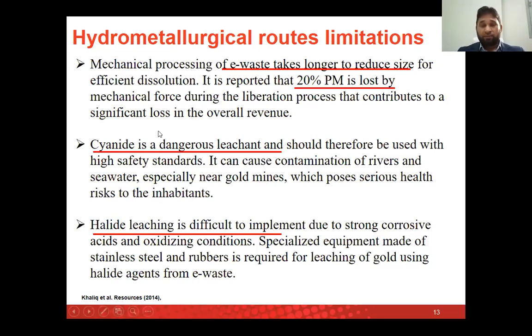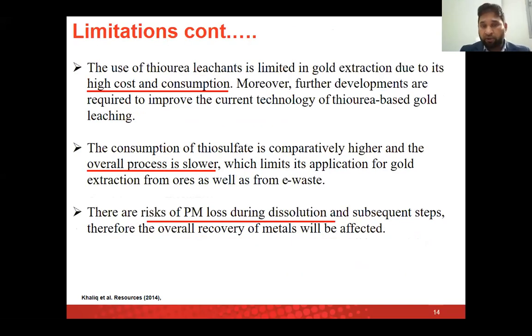Then the solvents or the acids that are used during the hydrometallurgical routes are not environmentally friendly. They are not recommended. Even cyanide is a very dangerous leachant. That's only used in gold mines with special protocols. And of course, they pose serious health threats to the inhabitants. The next approach in hydrometallurgy is halide leaching. Halide leaching is very corrosive, with corrosive and oxidizing conditions. Due to these limitations, you have to have special equipment, for example, stainless steel and rubber equipment. That's also not environmentally friendly and not easy.